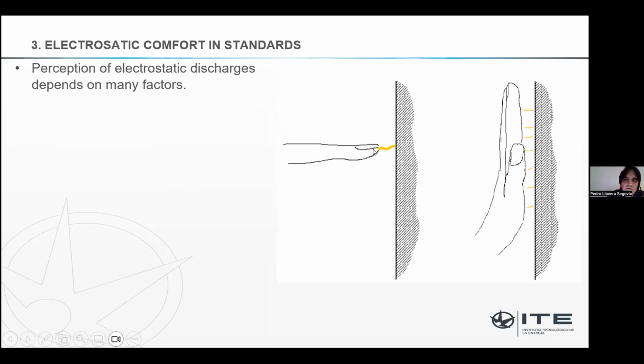If you are charged and you approach your finger to a wall, you have a discharge concentrated on one point, and it hurts because the current density is high where the discharge appears. But if you approach your flat hand to the wall and you have many simultaneous discharge points, the feeling is less strong. You can sometimes even hear the noise of the discharge, but you don't have pain. So you can make this simple experiment. Sometimes it works, not every time. It depends on the hand and the wall.